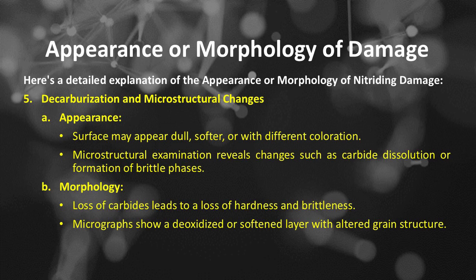Number 5 of the appearance or morphology of nitriding damage is decarburization and microstructural changes. The appearance would be a surface that may appear dull, softer, or with different coloration. Microstructural examination reveals changes such as carbide dissolution or formation of brittle phases.